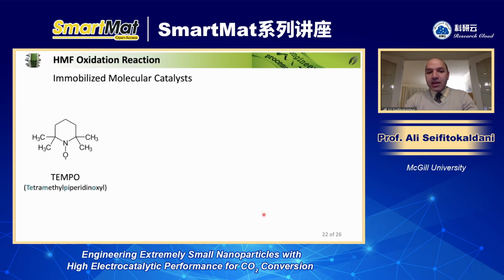So what we can do, people are using molecular catalysts like TEMPO, which has this structure, as the mediator or as the catalyst. But these types of molecular catalysts need to be dissolved inside the electrolyte. You still have the electrode, a solid electrode, which can be carbon paper, glassy carbon rod, or carbon felt, different sorts of conductive material. But then the TEMPO, for example, is dissolved in the solution. So these catalysts work perfectly. You can convert the HMF using these types of catalysts at very low pH, such as pH 7, 8 even. So you don't have any more degradation problem. The challenge is the catalyst is within the system.